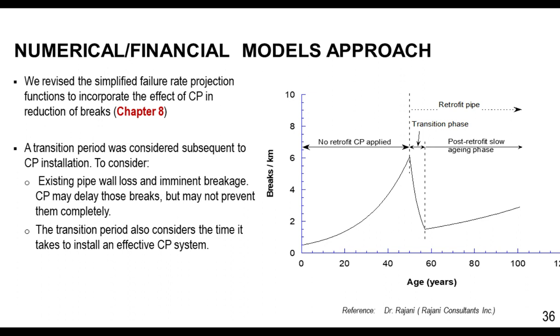So if there is already a significant amount of corrosion at some areas, those breaks are going to happen, and cathodic protection cannot undo it. But it's just going to happen at a slower rate. And also, as we are adding anodes and increasing our coverage, it would take some time, and that also is considered in the transition period.